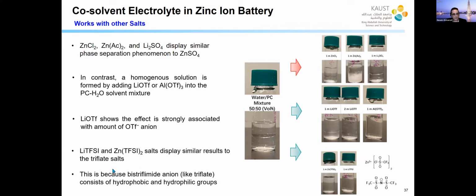So that means definitely this OTF is the reason why we're having these homogeneous solutions. We also found other salts, which are more complex, but they have both hydrophilic and hydrophobic ends, just like the triflate. This is a different salt now, and amazingly, it does the same thing. So this really shows that if you have an anion with two parts, one hydrophobic and one hydrophilic, you can essentially enable a homogeneous solution.